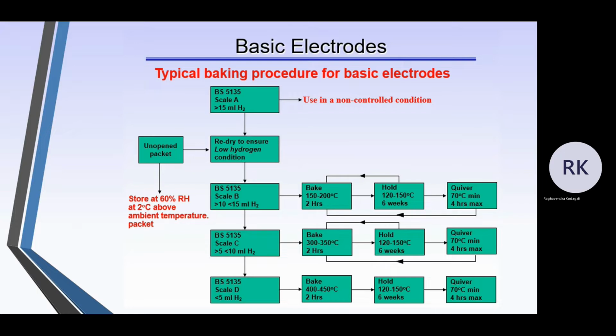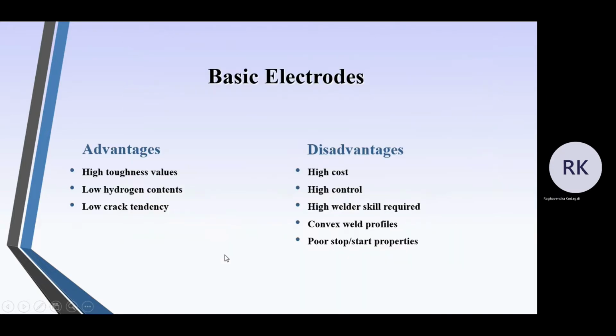So you can see the typical baking procedure for basic electrodes used in non-controlled condition. Unopened packets are stored at 60% RH and 2 degrees above the ambient temperature. Then re-dry to ensure low hydrogen condition. Then you have to bake it at 150 to 200 degrees for 2 hours, and then hold it at up to 150 degrees for 6 weeks, or whatever the manufacturer recommends, and then you have to put it in the quiver. Similarly, you have to do this for the other types of electrode also.